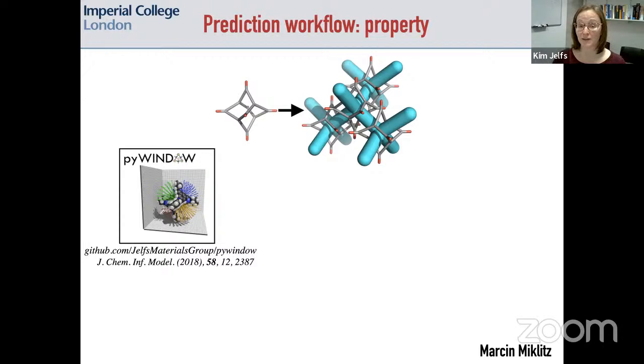And surprisingly, we found that actually the packing wasn't having as strong an influence on all those things like pore limiting diameter for the cases that we looked at as we expected, and therefore this approximation held quite well.